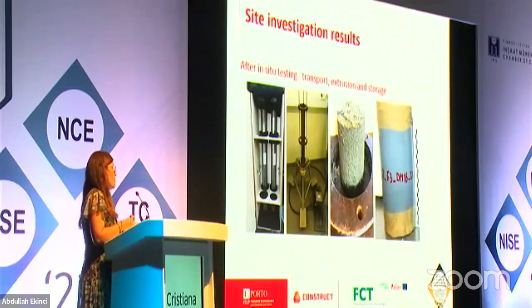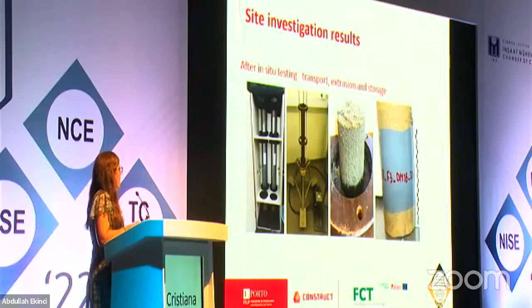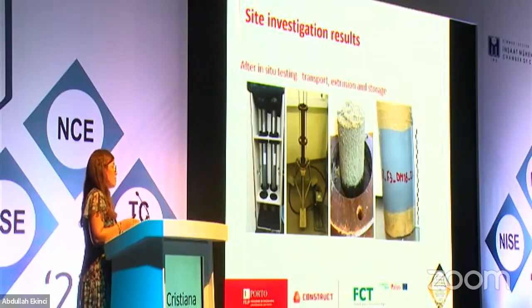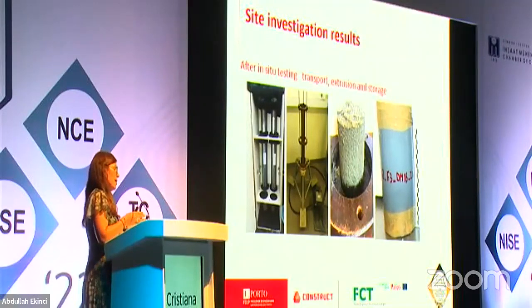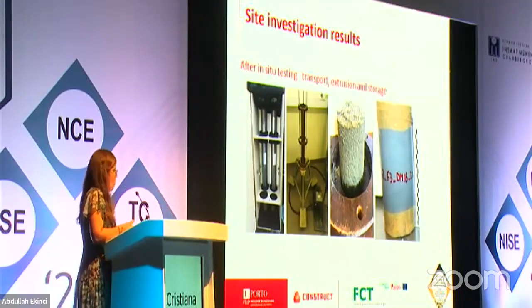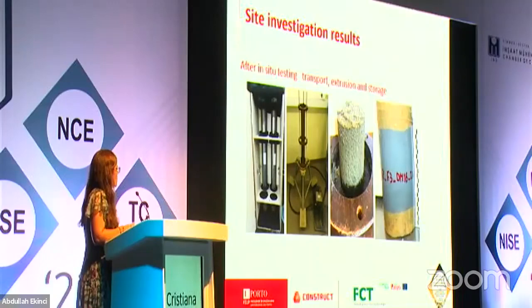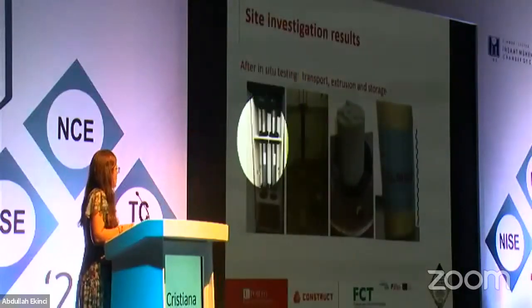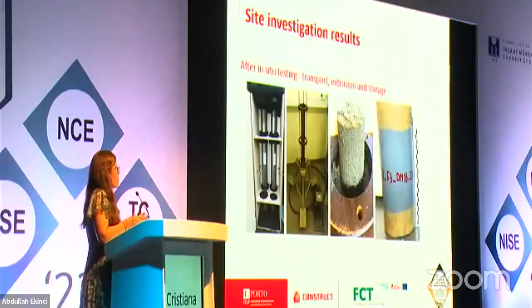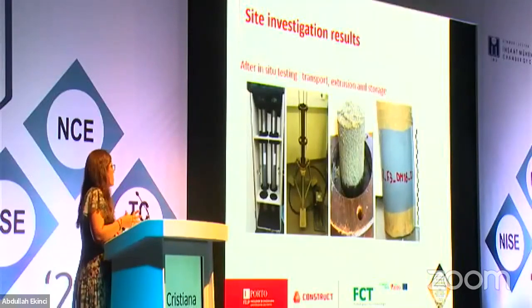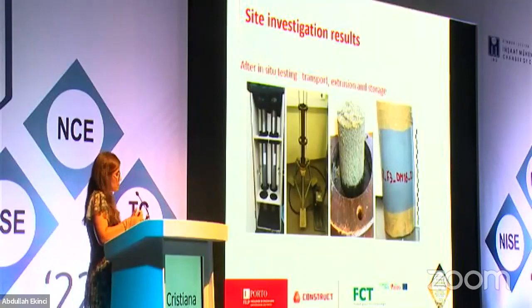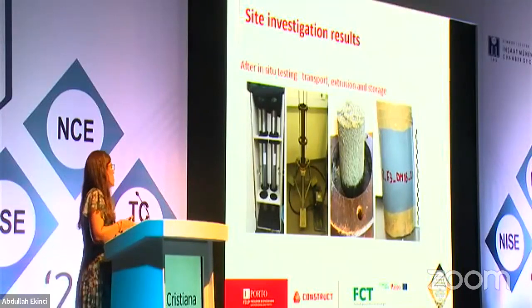Then another important aspect is that we want to test this in the lab, and for that, all the processes in high quality sampling are relevant to ensure that you don't disturb the sample until you test it. And it's not just the sampling process. So we were very careful about the transport, and for that we used specifically designed wooden boxes that were protected with some foam in order to make sure that the tubes wouldn't move during transportation.